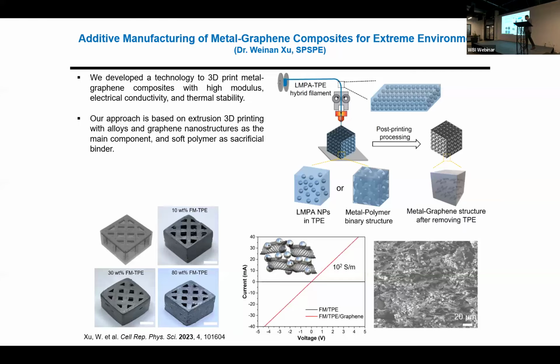So this first project is part of our additive manufacturing of metal composites. What's exciting about this is that Dr. Weinan Xu, who's leading this project, is doing fused filament 3D printing of these metal composites. These are low temperature, below 200 degrees Celsius, to print these parts. The way that's achieved is through liquid metal alloys. So gallium, indium, tin is a metal alloy that has a very low melting point. You can blend it with a polymer and then 3D print it as though it were a plastic.